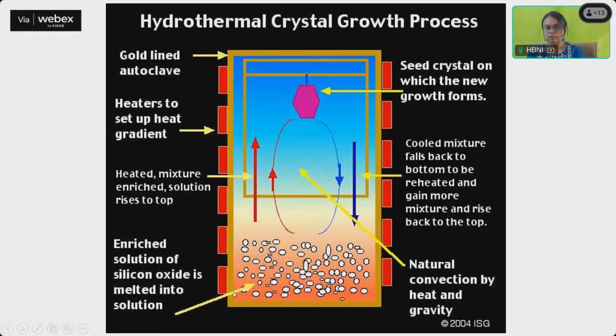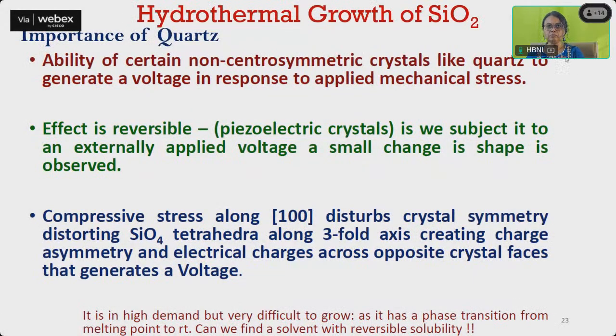So this is typically used, as I said, for the growth of quartz, the single crystal SiO2. Why is quartz important? I will briefly tell you. In the last lecture we heard about the importance of silicon, but why is quartz important? Because it is a non-centrosymmetric crystal, it generates a voltage in response to applied mechanical stress. Your watch has a quartz crystal. Compressive strength disturbs the crystal symmetry and distorts the threefold axis, creating charge asymmetry and an electrical charge across opposite crystal faces that generates a voltage. So this is piezoelectric.